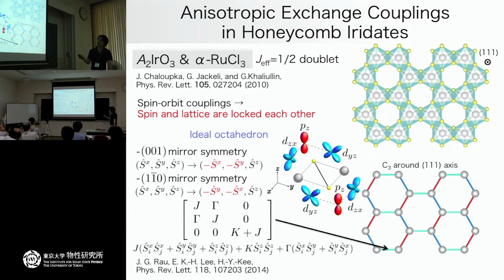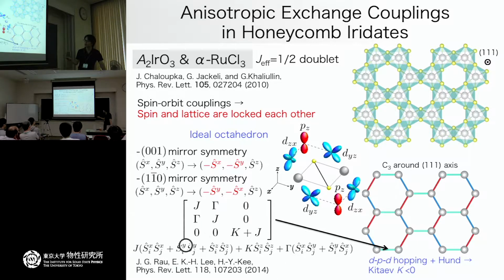J is the usual Heisenberg coupling, K is the Kitaev coupling, and gamma is the so-called off-diagonal exchange coupling, or we just call this interaction the gamma coupling. If you write down this Hamiltonian for this bond using spin operators, it looks like this, and this matrix form represents this situation. Usually, if we only have this kind of d-p-d hopping, and this hopping generates a spin-spin interaction among these two ions, then we only have a dominant Kitaev coupling. But in the real compounds we have several exchange paths, and through these exchange paths we introduce this Heisenberg coupling together with the gamma term. It was already examined by these people.